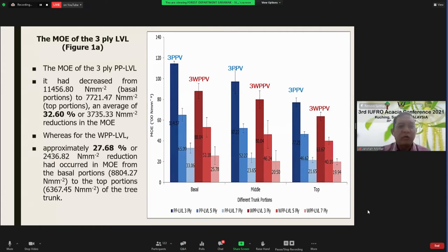The result shows that the MOE of the 3 ply prepressed veneer LVL decreased from 11,456 newton per millimeter square for the basal portion to 7,721 newton per millimeter square, an average of 3,735 newton per millimeter square reduction in the MOE. Whereas for the without prepress 3 ply, approximately 2,436 newton per millimeter square reduction occurred in MOE from the basal portion to the top portion of the tree trunk. Next.